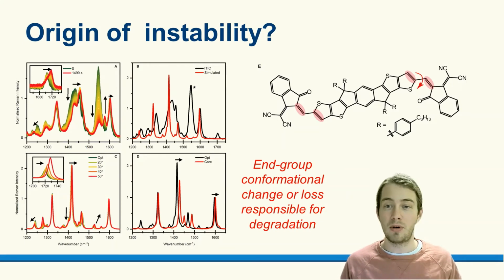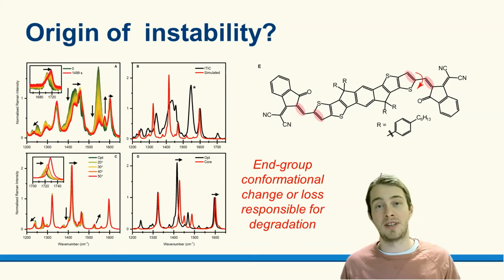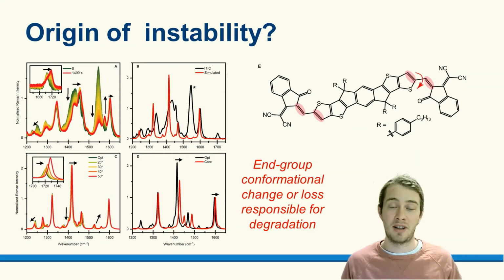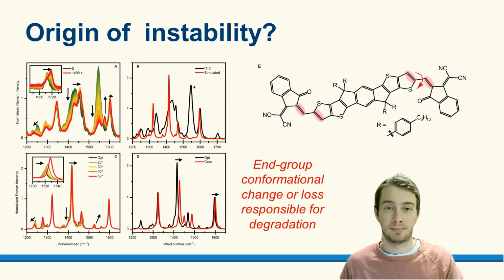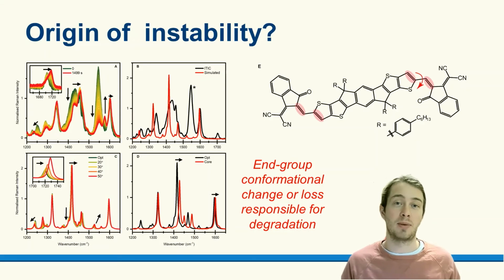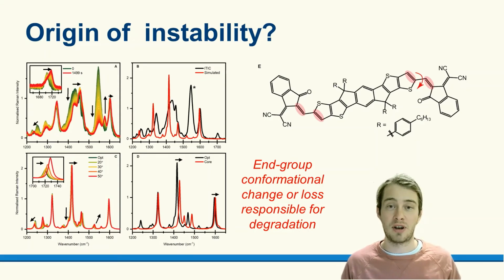And so by pinpointing this location of degradation as the end groups, and as this particular bond between the end groups and the core, this allows us to think about ways in which we can improve the stability of this particular material. And then, if we can improve the stability of this particular material, we can then improve the stability of the devices that we showed earlier.